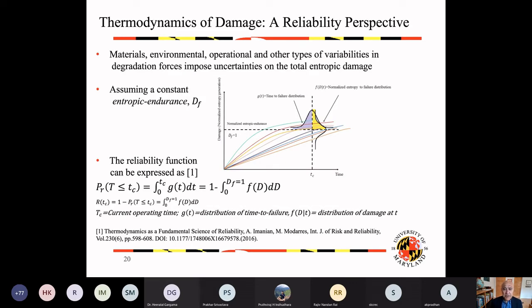So this brings me to the fundamental science of reliability based on entropy. I just showed you how entropy, which, as I said, is a measure of damage in our theory or in our vocabulary, accumulates over these paths to this level, which we call the normalized entropic endurance. Once it reaches this point, in our case a tiny crack of 250 micron was observed.